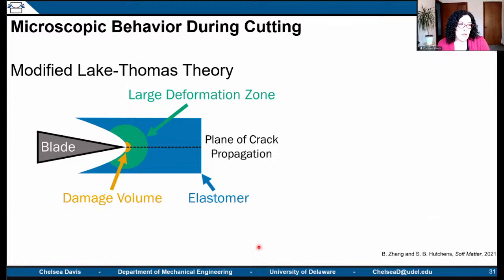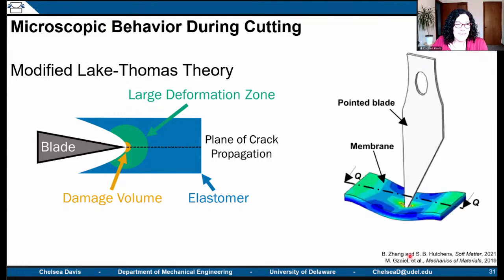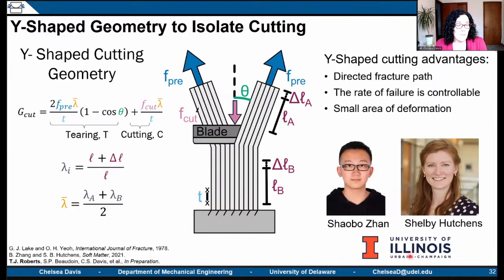So we're going to be utilizing a modified Lake Thomas theory that predicts a small damage volume. We can't see that, that's little. And then a large deformation zone that I think we can see with our mechanophores. So this green region is what we want to see if we can observe with our cutting experiments. And much of this is going to be drawing on the work out of Shelby Hutchens's group at the University of Illinois Urbana-Champaign, who brought to us the Y-shaped cutting geometry, which is going to allow us to isolate the cut directly over our microscope.